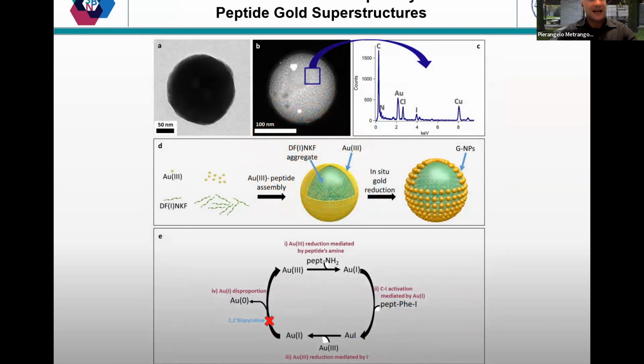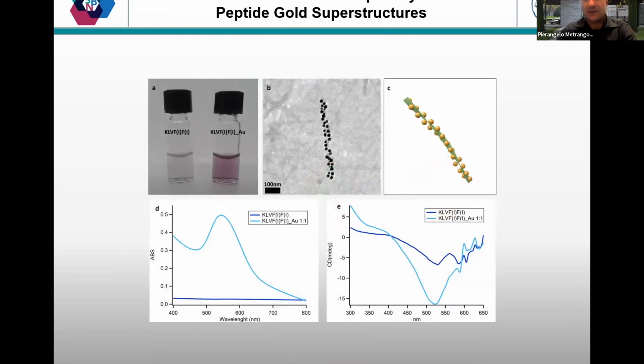It took some time to understand the mechanism, but we were quite happy because we understood that the presence of iodine starts the reduction of gold in a very complex system, which first self-assembles and then makes the reduction reaction. You can see more details in the paper. This was general, because other different peptides can also be self-decorated by gold nanoparticles directly in situ.